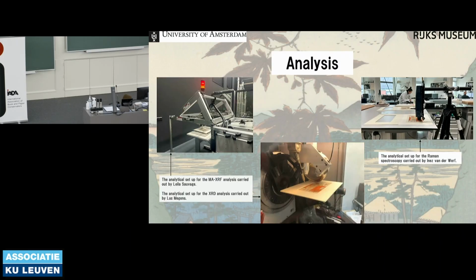So, first, I worked with Leila Sauvage and performed macro X-ray fluorescence on each of the prints to determine if there was indeed red lead in all these suspected areas, and if other elements of interest, such as sulfur, were also apparent in significant amounts. And then from there, I attempted to find an analytical method that could identify the source of the discoloration.